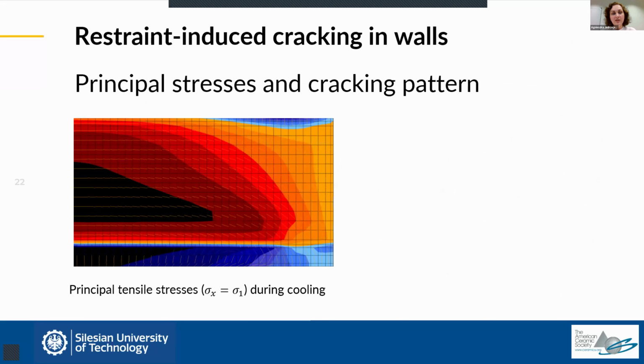So obviously, as I have shown, the maps of these stresses are pretty complex. So these stresses are variable within the volume of the wall. But what we can observe is that some simplifications can be made in a sense that when we look at the map of stresses along the length of the wall, they coincide with principal tensile stresses which are observed in the wall. So if we follow the trajectories of tensile stresses in the wall, we see that in the central part of the wall, the tensile stresses are practically horizontal, and the deviation starts to appear as we get closer to the end of the wall, which results from the warping effect of this end of the wall.